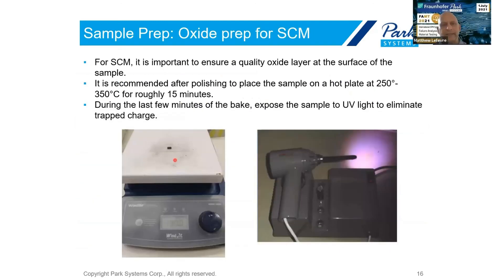One last thing on scanning capacitance: since we need a nice native oxide to get good images, we typically do a heat treatment around 250 to 350 degrees C for 10 to 15 minutes, and expose the sample to UV light during this to eliminate any type of trapped charges. With this, I will pass the baton on to Andreas to finish the presentation.